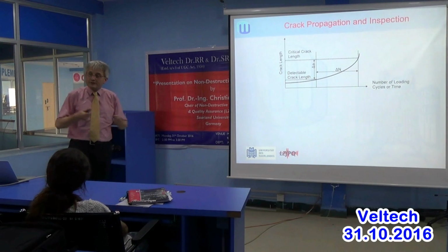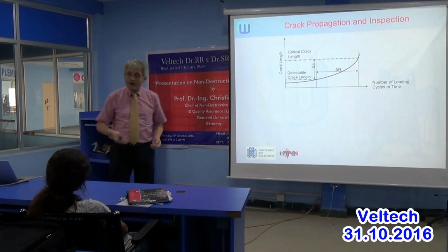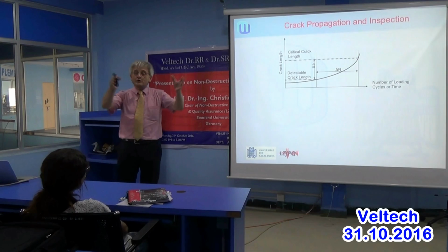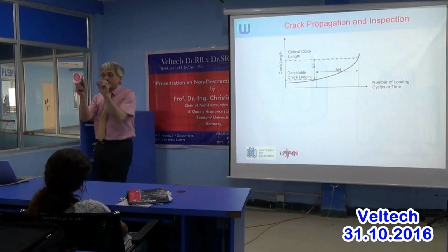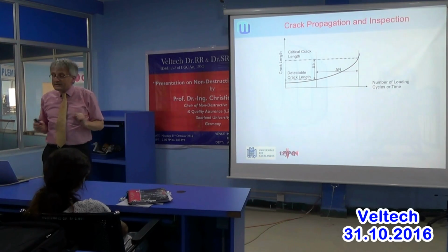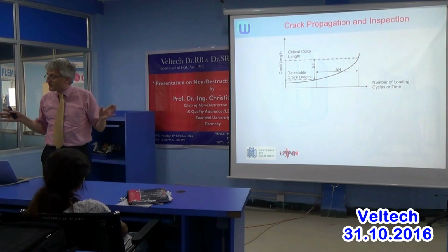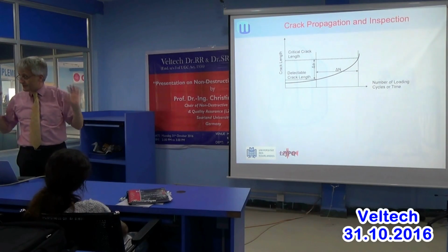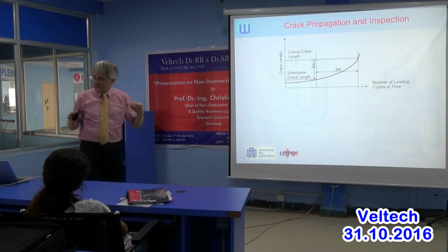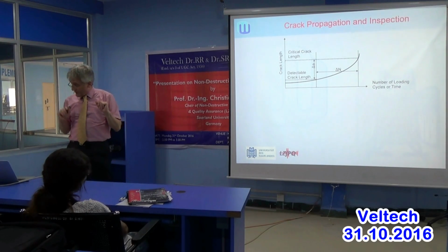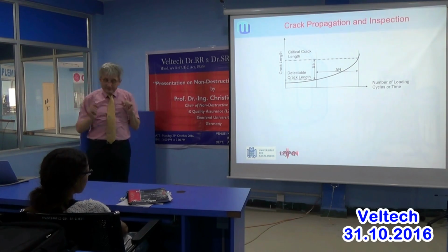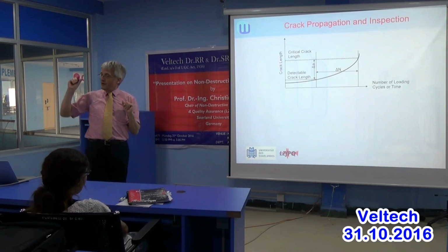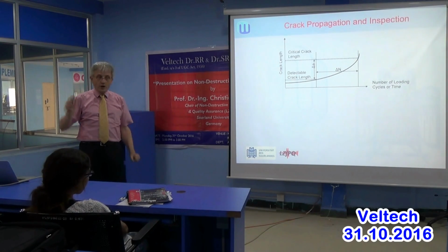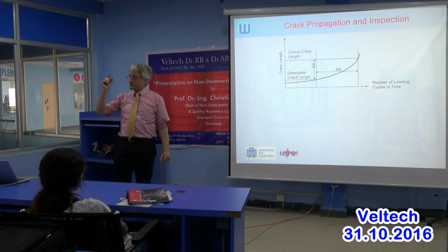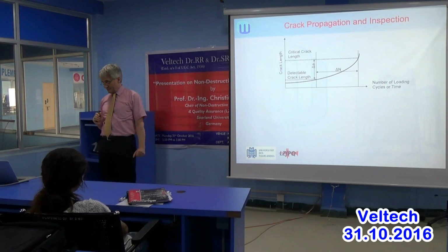Now if the structure has been used for a while, you cannot see a crack obviously, because those of you who know a little material science know there are micro cracks. So there's a micro crack, but nobody can see how big it is, so we don't know how big the micro crack is. And you've also seen it's difficult to see a specific crack length. At least we must have a crack length where we definitely know we have not missed a crack which is bigger than that size.